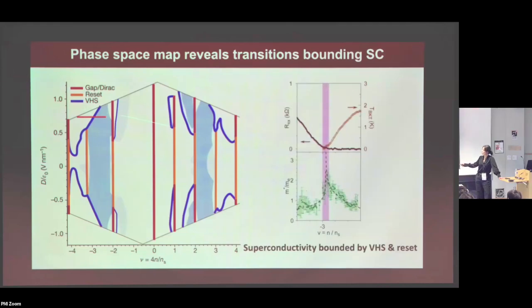Just to show you once more what happens at this kind of boundary at the Van Hove singularity, the effective mass diverges, so it confirms that you have a Van Hove singularity at this point. But at exactly the same point, because we can do the transport measurements, your Tc drops to zero and the resistance becomes non-zero, or vice versa. There's a transition point of the superconductivity exactly where this Van Hove singularity is happening. So that again tells you that superconductivity is bounded by these resetting features. So now we have a clue that superconductivity is only happening in particular symmetry broken phases that are bounded by these transitions.